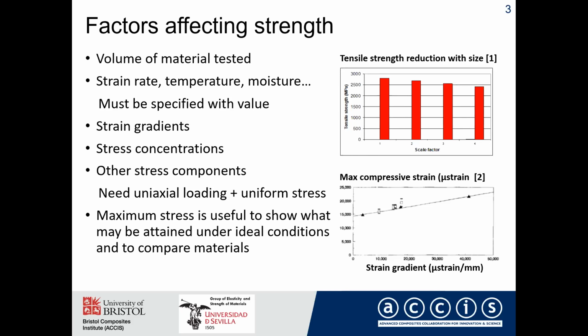Of course, there are many other factors which affect the strength: strain rate, temperature, moisture. And I think the key point is that these must be specified with a value. Other parameters which can also affect the strength are, for example, the strain gradient. This is particularly important in compressive failure. So on the bottom right, you see a graph of maximum compressive strain at failure plotted against strain gradient from some tests we did years ago using a constrained buckling rig. And you can see that as the strain gradient increases, so does the maximum compressive strain at failure. So we have to be careful to avoid strain gradients, particularly in compressive testing.